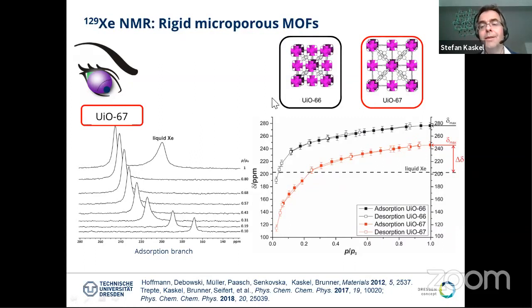And a very nice model system in this case is the UiO-66, which is a very stable and rigid system. The 66 has the phenyl linker, the 67 has the biphenyl linker. So we see the impact of the pore size in this system. And here, these are typical xenon NMR spectra with respect to P over P0. So at P over P0 of 1, we see the liquid xenon, which has a chemical shift of about 200 ppm. In this isotherm, this is shown here as liquid xenon with 200 ppm.